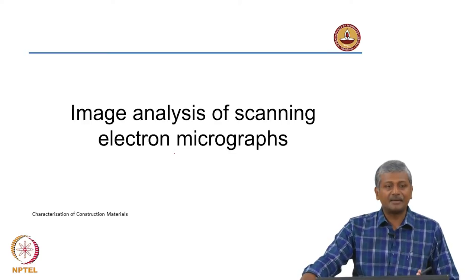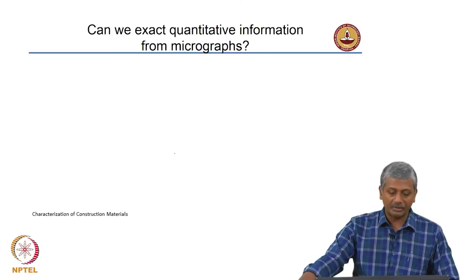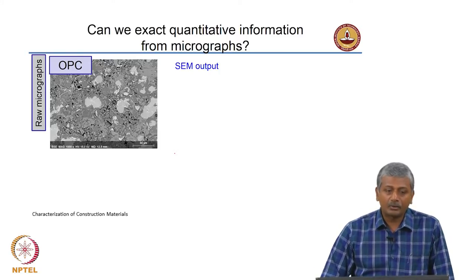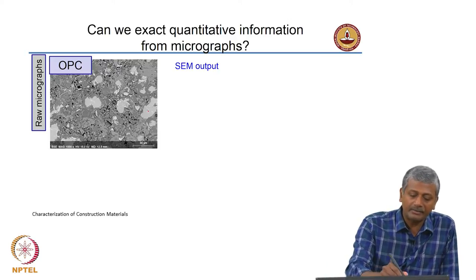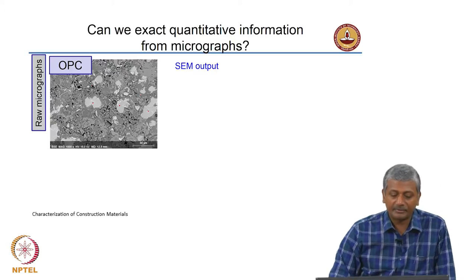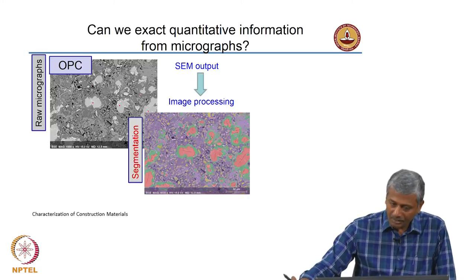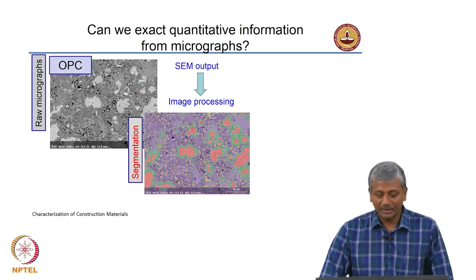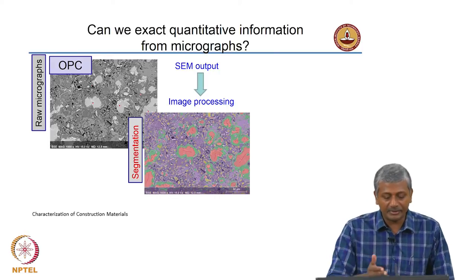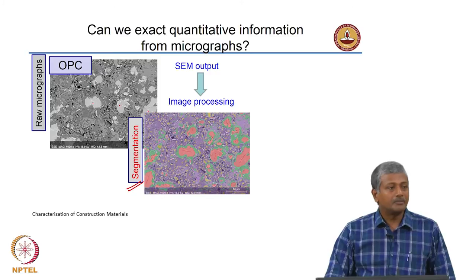We will now talk about image analysis of SEM micrographs, because that is where we need to get a lot of information on the distribution of different types of phases inside a cementitious matrix. For example, here you have an ordinary Portland cement paste micrograph showing the phases. You have the unhydrated cement grains, voids which appear completely black, and much smaller pores inside the cement paste. In between the black and white there are different levels of shades of grey. When you do image processing and thresholding and determine the exact grey levels where you can cut off one phase and describe another, you can do what is known as segmentation — separating out the different phases represented by the image elements.